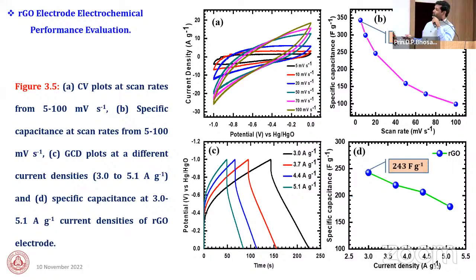Then I studied electrochemical study of RGO electrodes for negative electrode purpose. That's why I'm using negative potential window for a CV and GCD calculation, also for different scan rates and different current densities and the specific capacitance calculated using CV study. And this is the 343 farad per gram at 5 millivolt per second. And for charge discharge study, this is the 243 farad per gram at 3 ampere per gram.